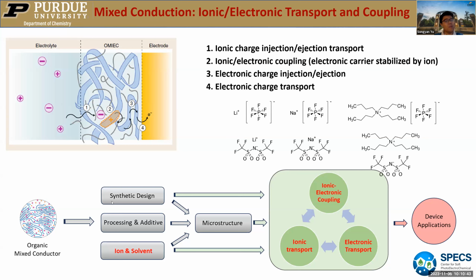To understand this, there are many different ways we can tune the structure. We can have different processing strategies. A simple way is just to change the electrolyte to see what happens. All these strategies will alter the microstructure of the polymer, and also alter the ionic transport, electronic transport, and ionic-electronic coupling. And then we will have different device performance. So what I've done here is not difficult. I just changed the electrolyte. We know it's an n-type polymer, so first I change the cation. Here we have lithium, sodium, and TBA. Some literature has also reported that the anion can play a role in this transport behavior, so I also changed between two anions, PF6 and TFSI.